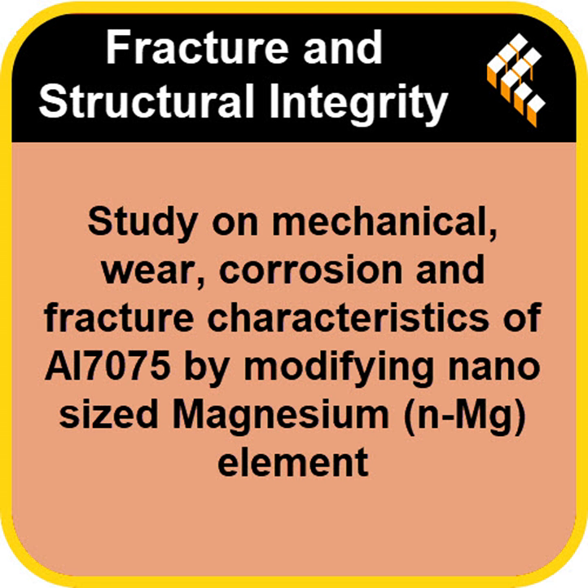So what does this all mean? It means we have defined a profound engineering trade-off. The modification with nano-Mg absolutely achieves its goal of dramatically improving key mechanical properties. The 9.21% strength gain, the 18.82% wear resistance, those are tangible benefits. And the optimum strength dose is at 2 weight percent. Right. But that high performance comes at the expense of two critical vulnerabilities: a massive 35% reduction in impact toughness and a significant acceleration of corrosion.